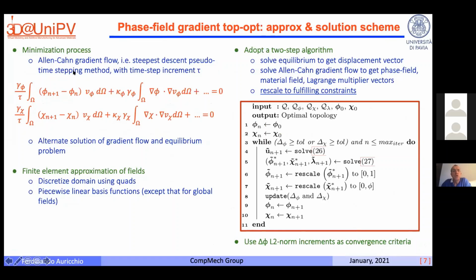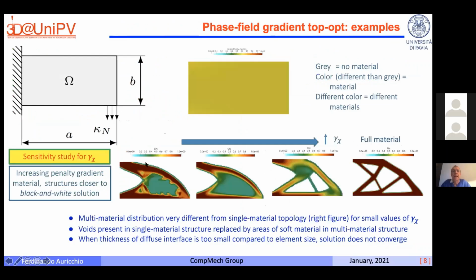So we introduce a sort of evolutionary solution algorithm where you can see that you solve incrementally the first phase field variable and the second phase field variable. And we develop a two-step algorithm. So the two-step algorithm, basically there is one step in which we solve equilibrium and another step in which we progressively solve the gradient flow and update our phase field variable. Clearly, you can then discretize using finite elements, and the very nice thing are basically the examples you can produce.